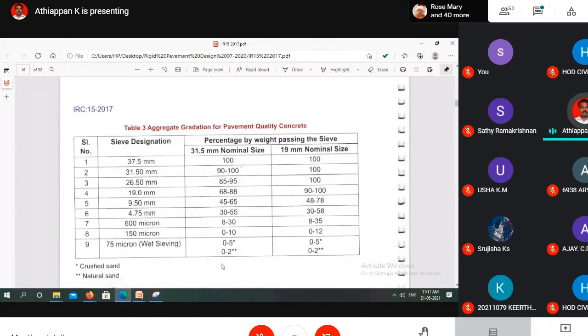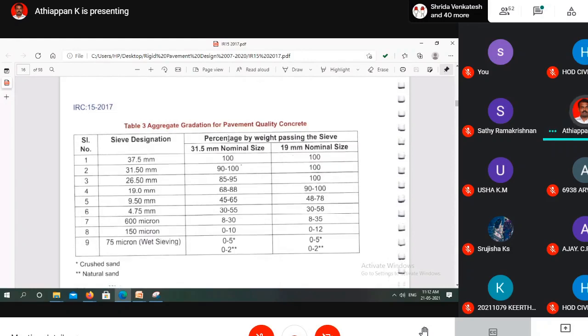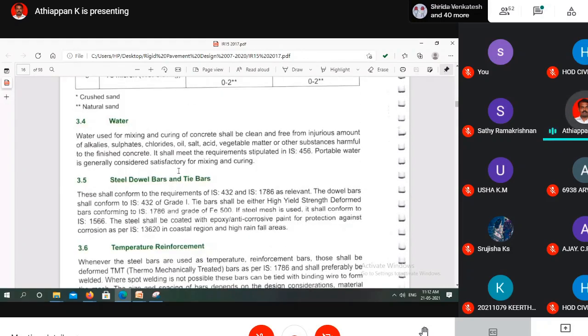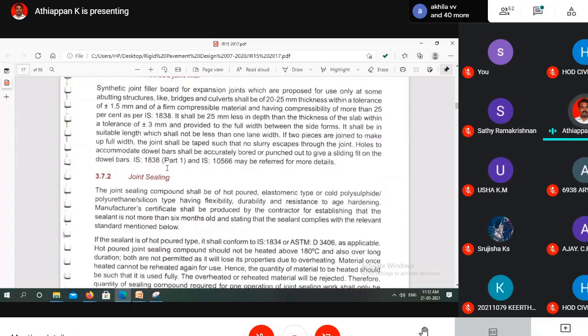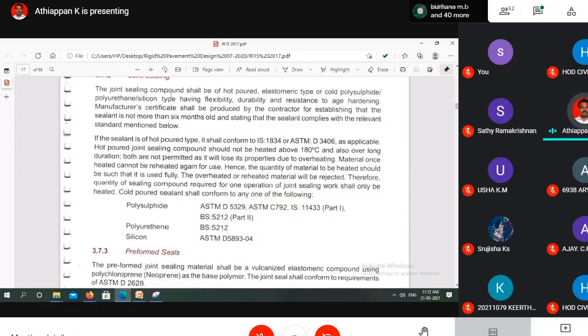Okay, then for pavement quality concrete, we are using one type of aggregate, that is maximum size 31.5 mm, and another size, that is maximum size 19 mm. So this is the particle size requirement for the broken stone aggregate required in the construction of the PQC. The aggregate used should satisfy any one of these gradations. Otherwise, the aggregate cannot be used for the pavement construction. Okay, so then water, dowel bar, all those things they have explained here. Filler, joint sealing, how it should be, like that they have given.